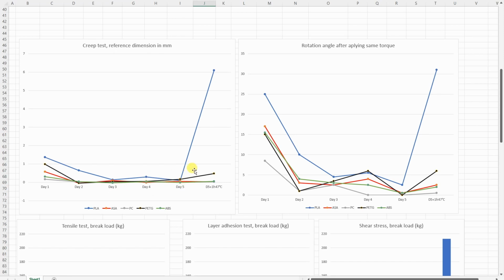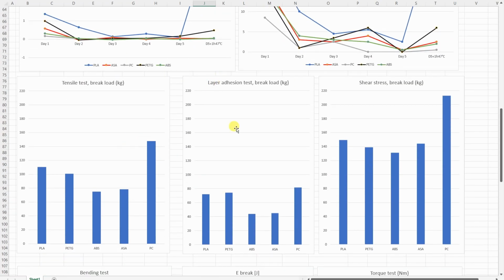But you can see after the heated enclosure, the PETG couldn't handle that temperature so well, but especially the PLA. So definitely 47 degrees Celsius is too much for the PLA if it has some constant load on it. And very similar results with that screw test. So the PLA showed the most creeping. The best was the polycarbonate in this test.